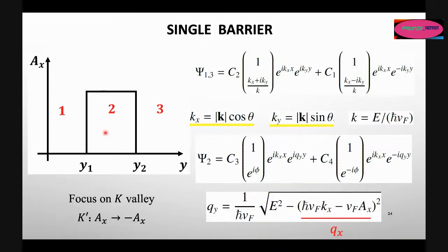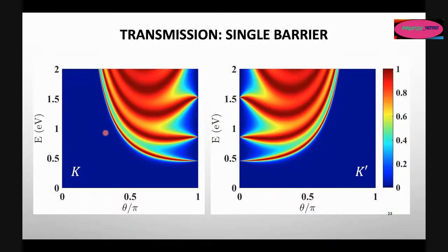So basically, what we do is a single barrier potential, and we calculate the transmission for the single barrier. You see that the red represents extended states for different angles of incidence towards the fold, states from valley K and K prime, and there are regions where they do not overlap. So if I create a wave packet with electrons that have momenta from both valleys, and make them incident on a fold at a certain angle, let's say 30 degrees, the states coming from valley K will have transmission 0, while the states in the wave packet that come from valley K prime will have, at different energies, finite transmission 1. So after going to the other side of the fold, I will have states from one valley only.